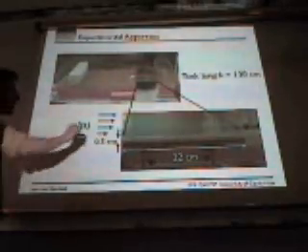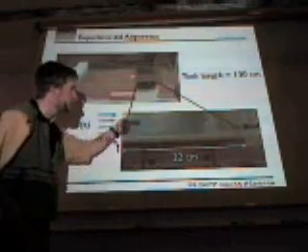So you can also do some experiments on this kind of system, and I've done some of those experiments for my PhD thesis, in which we took a flume with a cold plate, and this enabled us to apply a shear flow through the flume by introducing fluid on the left and having it flow over this test section or cold plate and being collected in this reservoir at the back and recycled to the front. And essentially what we did was to grow a mushy layer of a particular thickness off of this cold base plate, and then look at the stability of that mushy layer to a shear flow applied over the top.